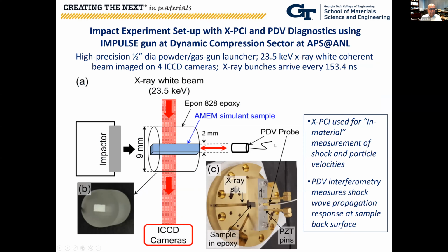Let me show you the experimental setup schematic. There's a particular gun called the impulse gun, about a half-inch barrel diameter, that can be used with either powder or gas to launch the projectile. A 23.5 keV X-ray white beam is imaged on 4 ICCD cameras, and these X-ray bunches arrive every 153.4 nanoseconds.